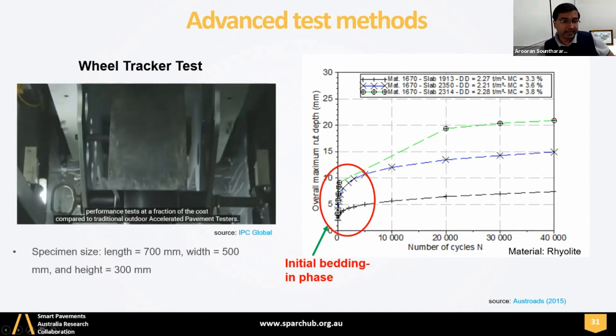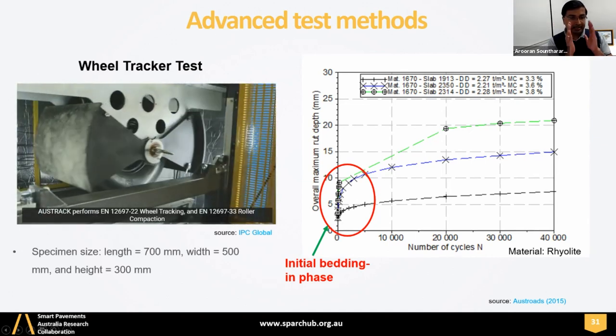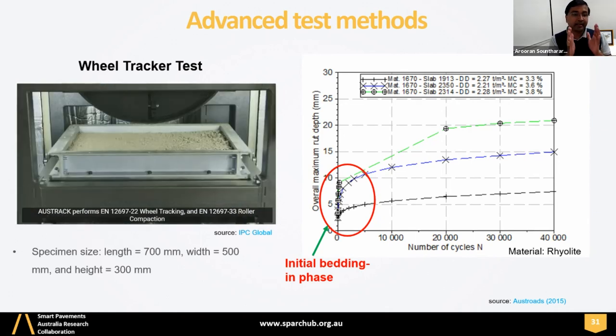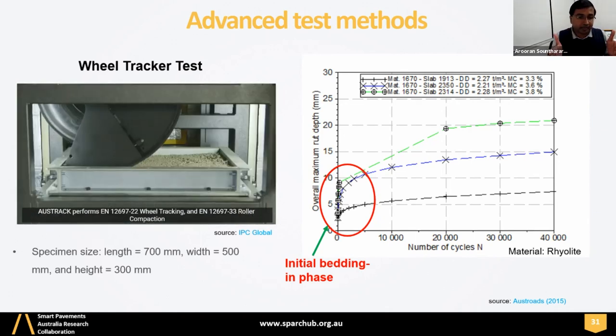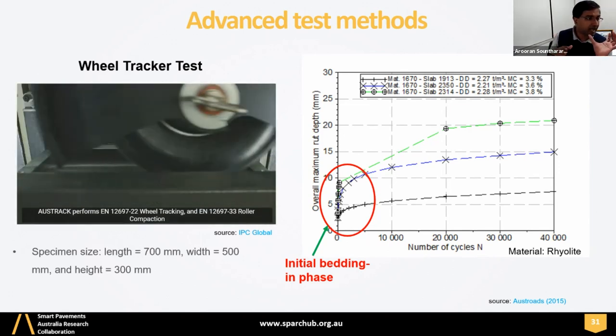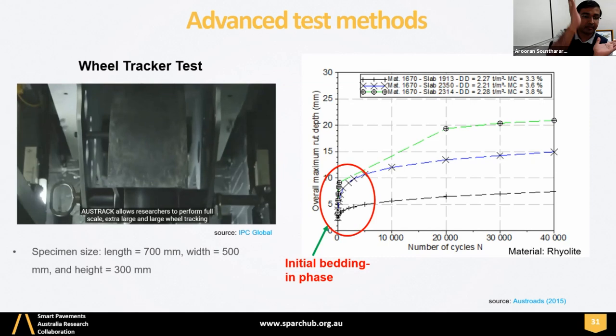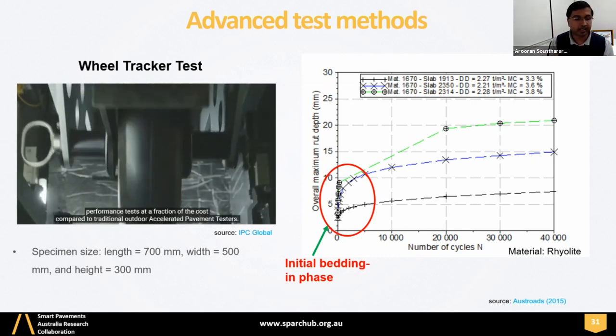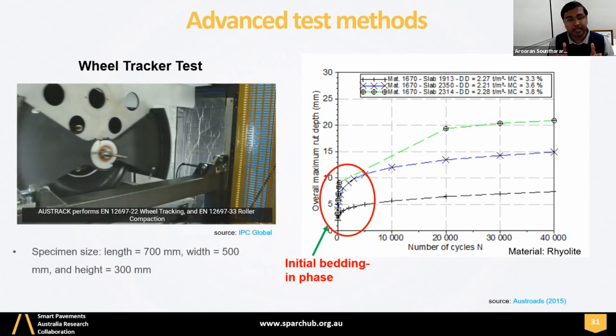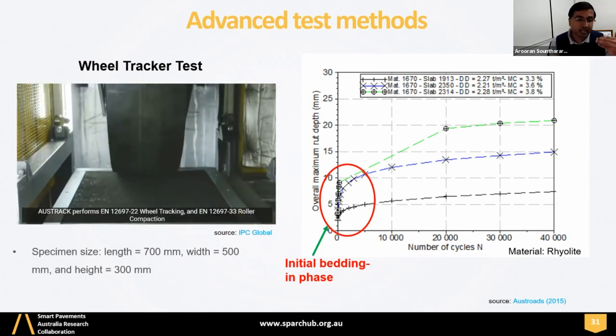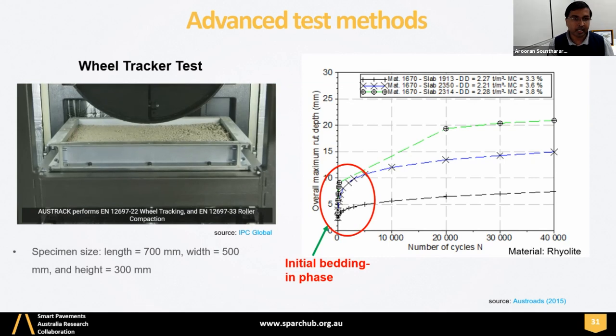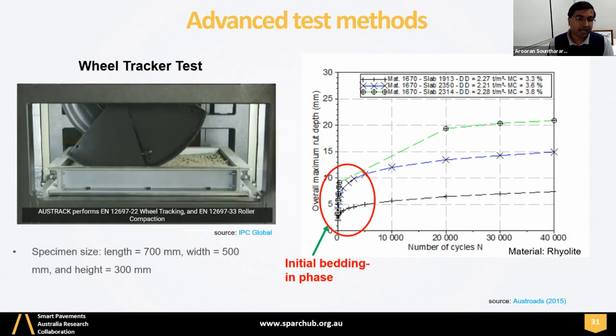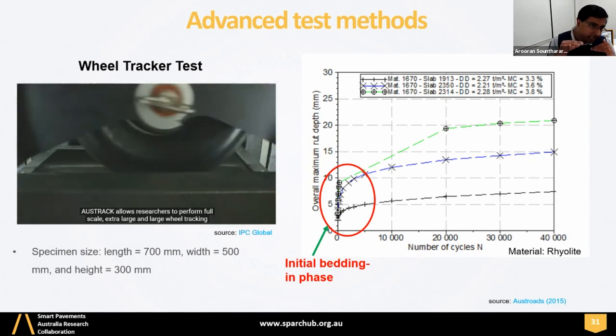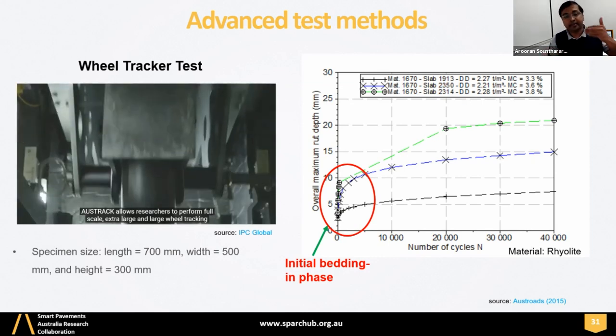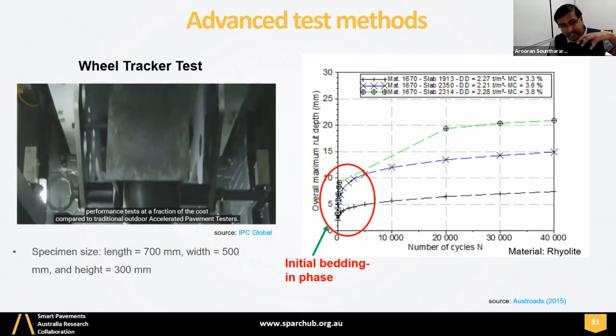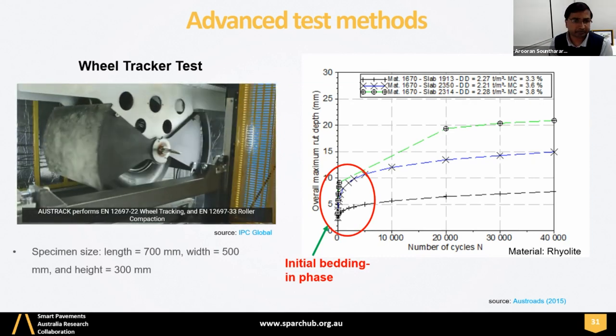So what happens here is, in the triaxial, the sample size is too small, but here you are having a larger sample, right? In triaxial, the typical size is 150 millimeter diameter, and the height is something like 300 millimeter. That's the element. But here you are compacting the pavement layer into a large box, 700, 500, 300 is the large box. And you see the compaction procedure here. So what happens here is you compact the material into that large box, right? And then you traffic the compacted layer using this setup, right?